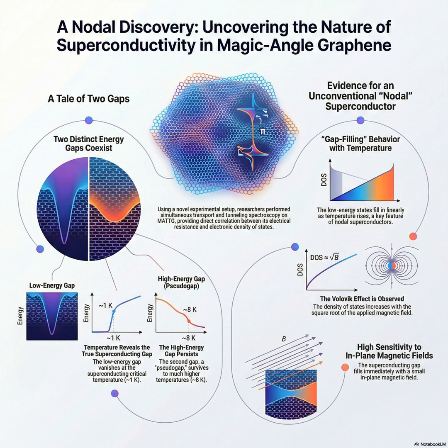Okay, so now compare that to the second one, the higher energy gap, delta PG. This gap was broader, shallower, and much, much tougher. Well, when they cranked up the temperature past T-C, the low energy gap disappeared, but the delta PG barely even flinched. Seriously? It stubbornly persisted up to around 8 Kelvin. That's 8 times higher than the temperature needed to kill the actual superconductivity. So this high energy gap is sticking around long after the party's over.